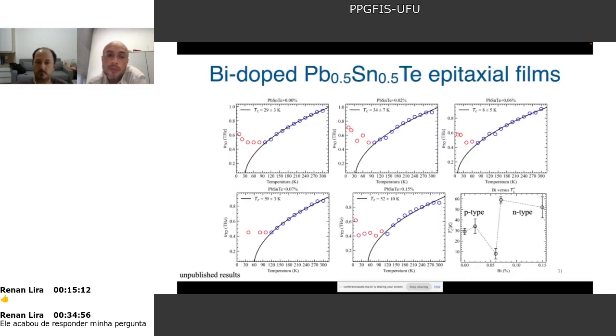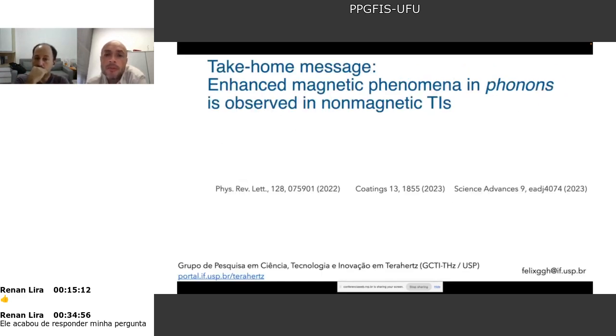We start by looking at the ferroelectric transition as a way to characterize whether the carrier concentration is changing. And we saw that you can see some change in critical temperature when you increase or decrease the concentration. This is something people know. It had been published that there is a direct relation between the critical temperature for the ferroelectric transition and carrier concentration.